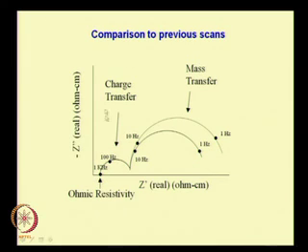Okay. So for example, this is a very simplified situation, but a very useful piece of information that you will get from it is that for the 2 experimental conditions in which you have tested your system, the ohmic resistance associated with the ionic processes and so on in the system has not changed for both the conditions. The charge transfer, if we have associated this section here with charge transfer processes in the system, has also not changed. What has really changed is your mass transfer. Okay. So therefore we are able to use this as a very powerful diagnostic tool.